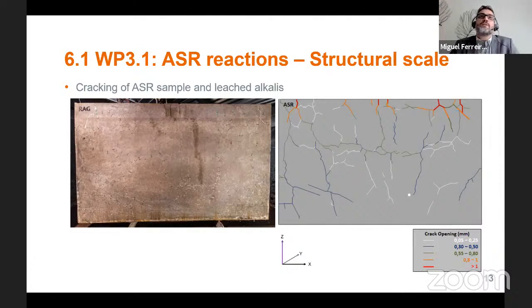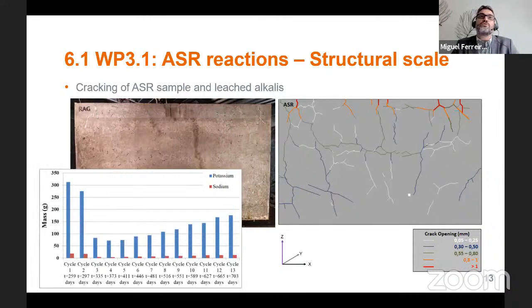And we measured the cracking index in each of these cycles as well. And we also measured the leaching of the alkalis in the pool water that was used to keep the humidity in the block at the right temperature. We observe a large longitudinal crack at mid-height and lots of vertical cracks, especially on the top of the block. And as we come to the bottom of the block, we see that there the cracking is smaller and the crack width is also smaller.